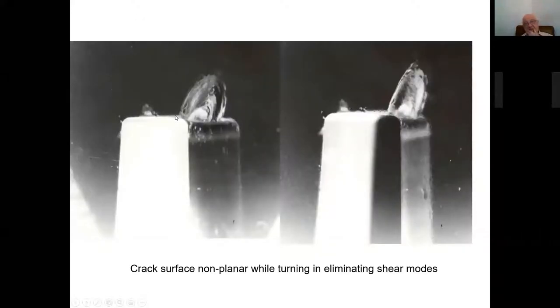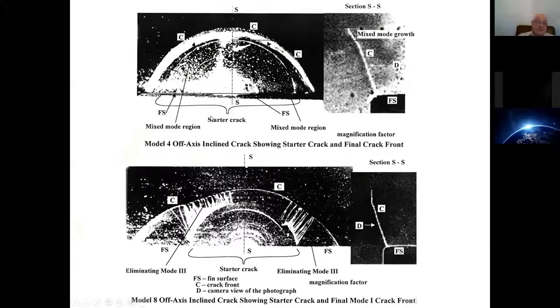Here you have two of these cracks, just to see a little bit how these are photos taken before slicing the crack. You have some initial crack here, and then this is naturally grown. These are only two examples. Mostly I wanted to show you that the surface of the crack doesn't remain planar during growing. So you can have all kinds of issues.